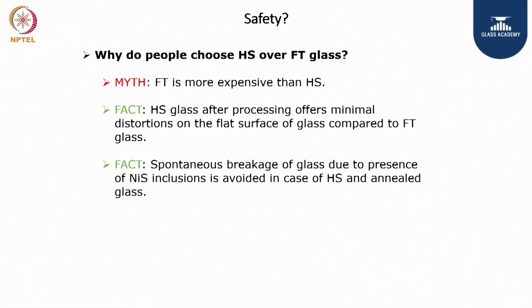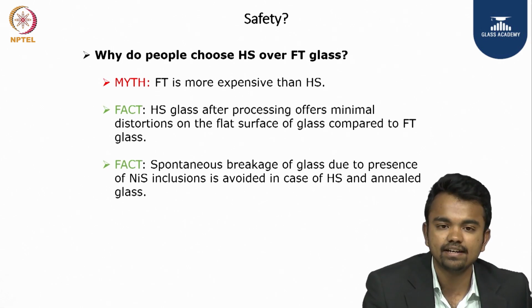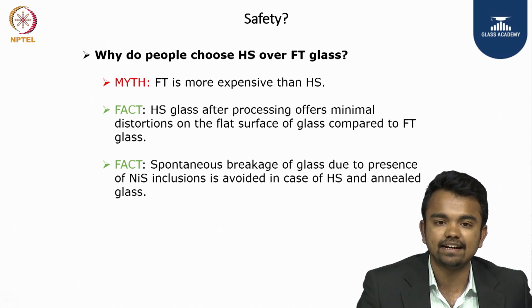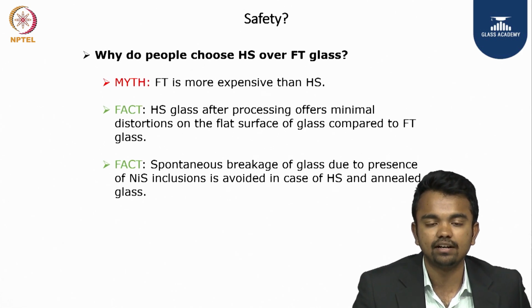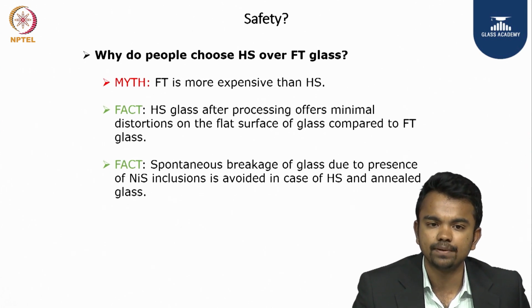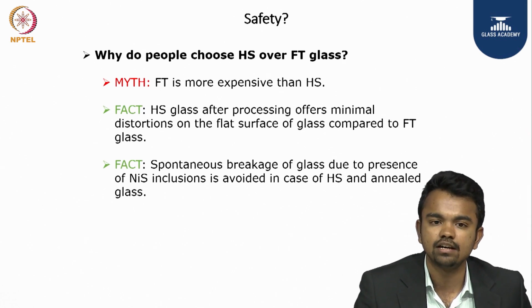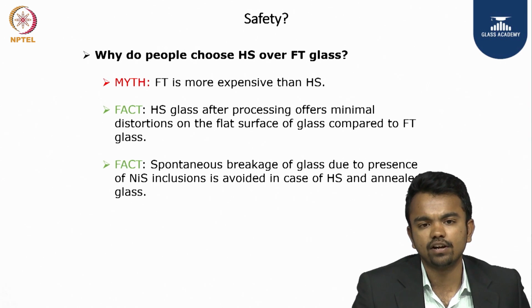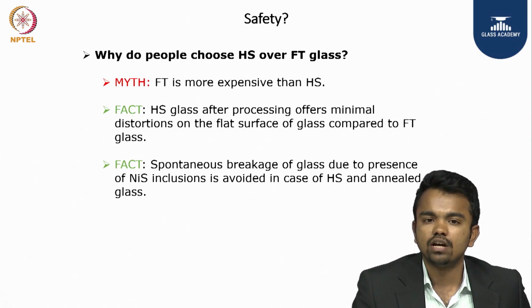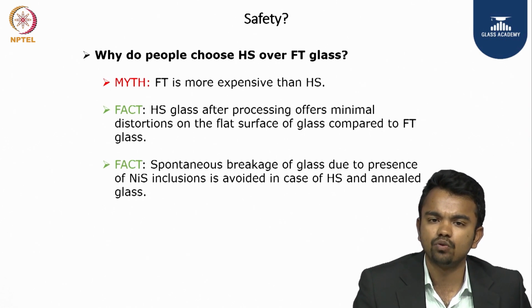One more fact is that spontaneous breakage of glass due to the presence of nickel sulfide inclusions is avoided in the case of heat strengthened glass and annealed glasses. One more reason why architects or consultants prefer heat strengthened glass over fully toughened glass is that spontaneous breakage cannot be estimated, and it cannot be said with certainty when it is going to happen. It may happen a day after installation onto your building, or even 10 years after installation, and whenever it happens, it will cause a very small explosion of sorts which will create a lot of noise, and it may be difficult for the end user to replace it also. So this is one of the reasons why heat strengthened glass is preferred over fully toughened glass, despite fully toughened glass being stronger.